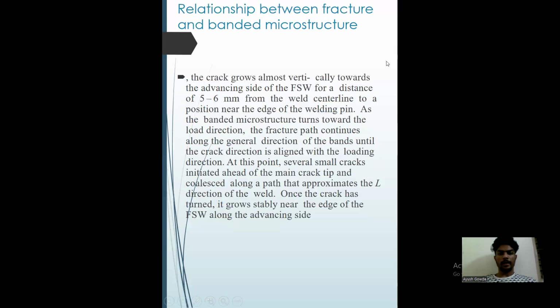Relationship between fracture and banded microstructure. The crack grows almost vertically towards the advancing side of the FSW for a distance of 5 to 6 mm from the weld center line to a position near the edge of the welding pin. As the banded microstructure turns towards the load direction, the fracture path continues along the general direction of the bands until the crack direction is aligned with the loading direction at this point.